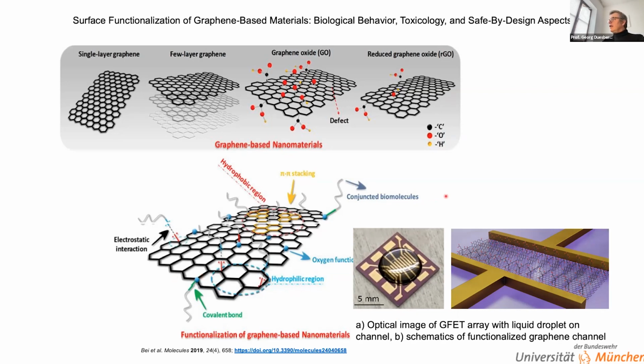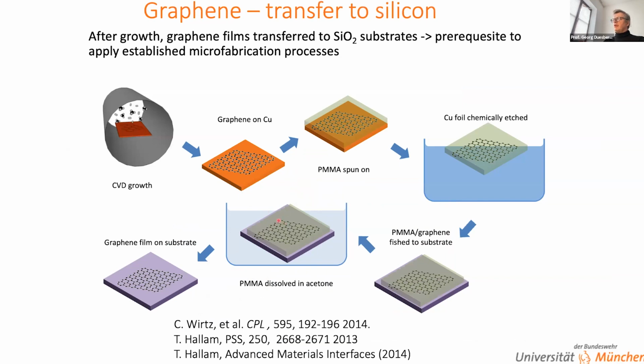So let's have a look how we do this, because the starting point is always this, that you grow your material by CVD on copper, and as shown before, similar to the skin electrodes, you then have to transfer it with a wet transfer, usually with PMMA, onto some sort of a substrate. This has been investigated by a lot of groups. There's nothing special to it.